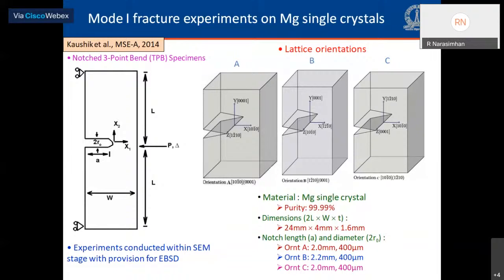As I said, one of the ideas was to look at the lattice orientation. So we considered 3 lattice orientations, which I'm going to call A, B and C. A and B are shown in the right side schematics. The C-axis, which is the 0001 axis of the hexagonal lattice, is along the normal to the flat surface of the notch, while the direction ahead of the tip and along the crack front are switched around between these 2 geometries. If you look at orientation C, the C-axis is along the thickness direction.